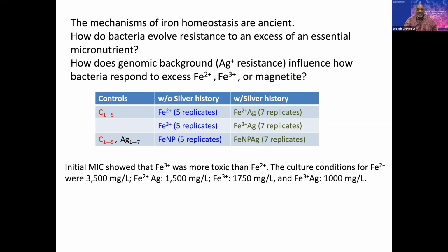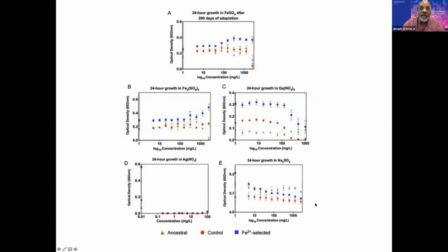So we tried to find something that left about 10% to 15% of the bacteria surviving in the presence of excess iron. And for iron 2, that turned out to be about 3,500 milligrams per liter of iron 2. And this was iron 2 sulfate. Now, here are the results of this experimental evolution. We had evidence of iron resistance as early as 50 days.